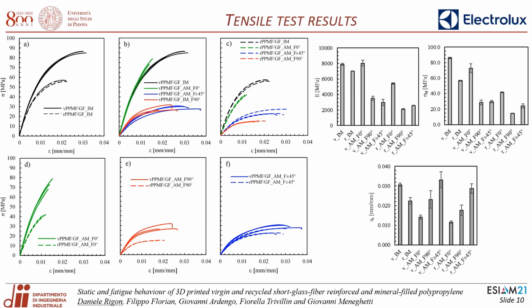On the contrary, the infill patterns F45 and F90 show a lower elastic modulus and tensile strength, but comparable elongation at break with respect to the injection molding ones. The same trend just discussed can be observed in figure C, where in this case the F0 degree stress-strain curves are not overlapped as well as the previous ones, and the F45 has higher mechanical properties than the F90 degree.